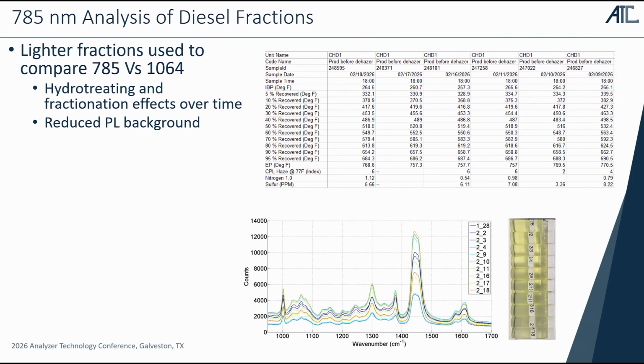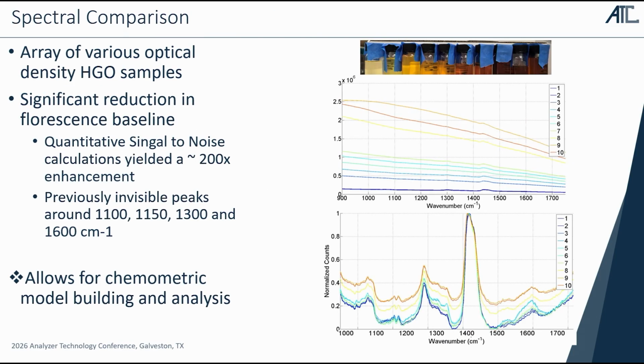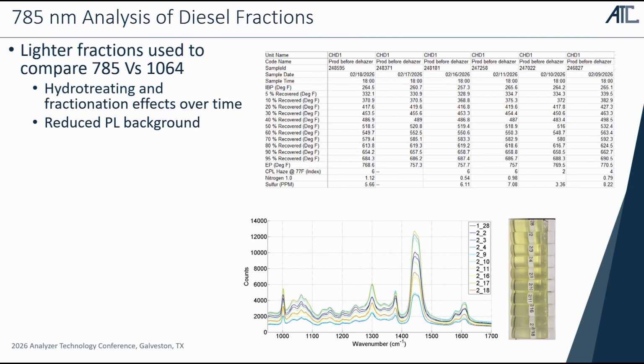And so the next experiment that we ran, we were trying to build a case for why 1064 is important. Not only can you access samples that are previously inaccessible, we want to make sure and validate that 1064 Raman can be used in applications that 785 is important for as well. So we shifted just slightly from the heavier, really dense hydrocarbon samples. We shifted a little bit to the left, where 785 is still useful in that regard, but maybe we can see some reduction in that baseline further, and also validate that 1064 can be useful in those applications as well.